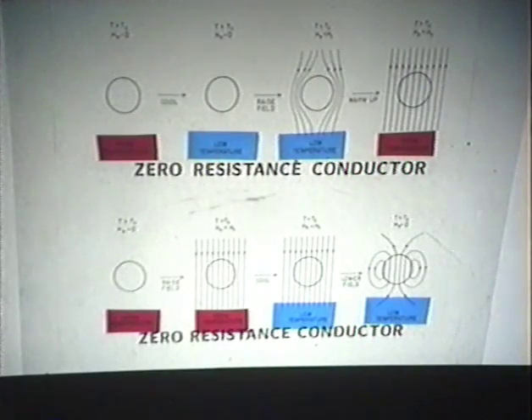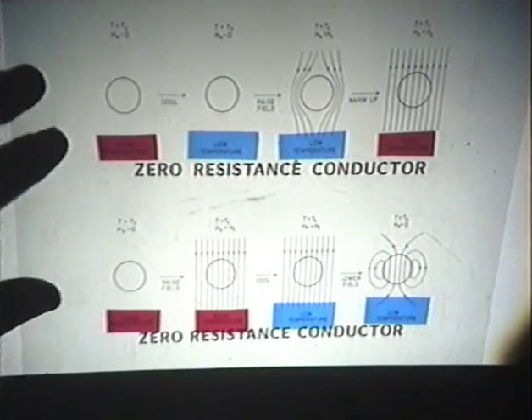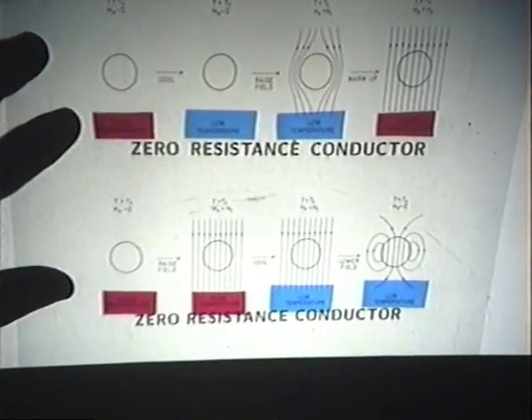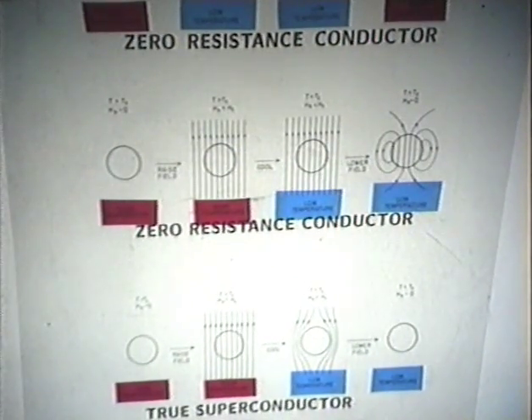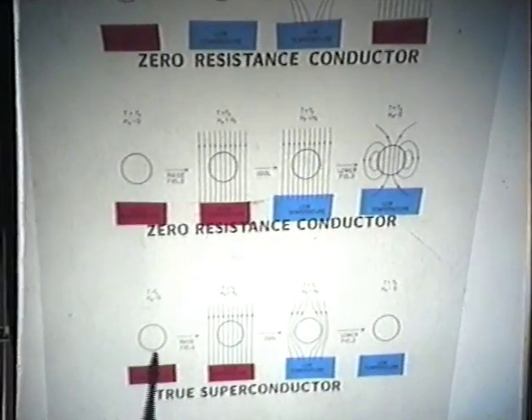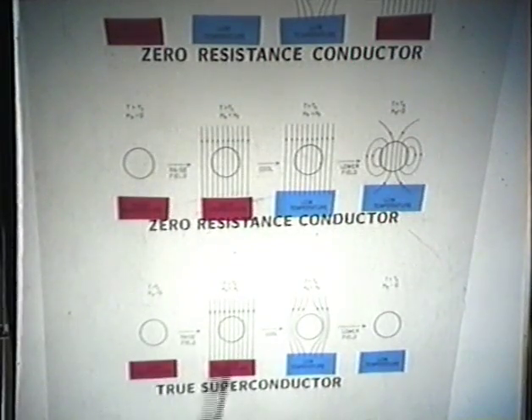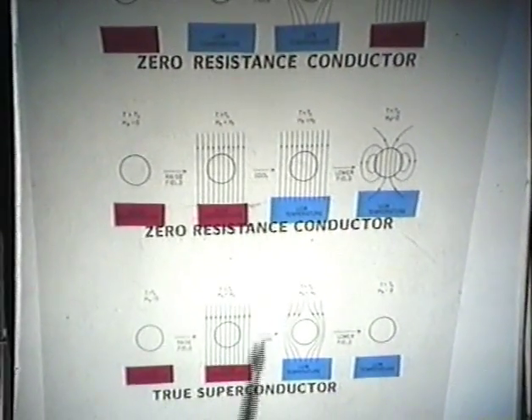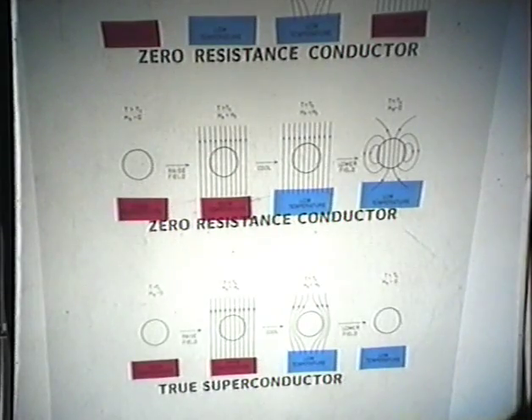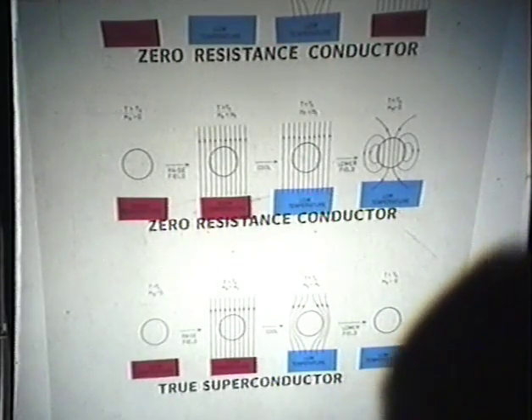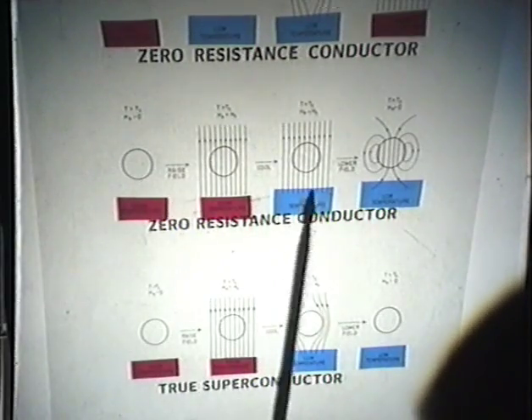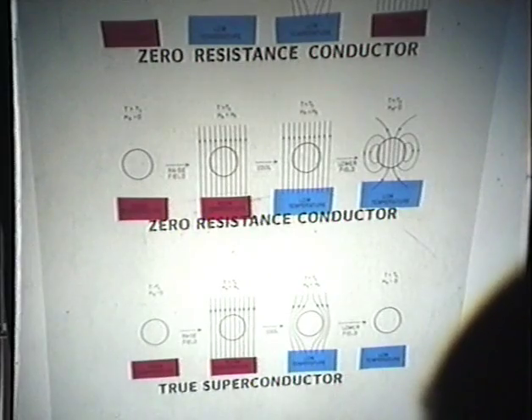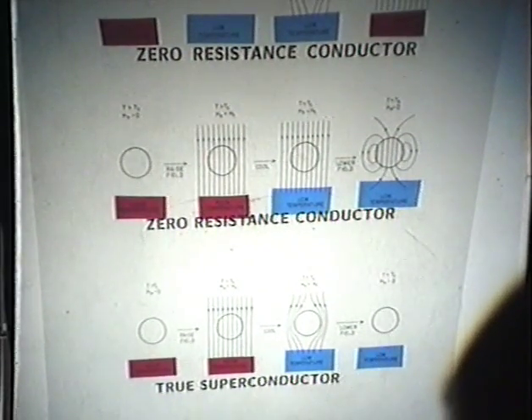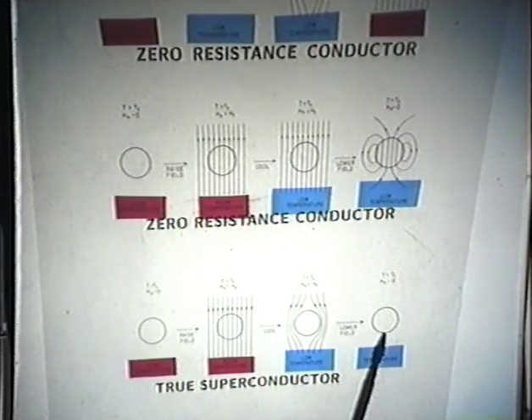So people did these experiments with the superconductors, these ones, niobium and lead and mercury and so forth. And this is what they got. A sensational result. When they took the superconductor at room temperature, put it in a magnetic field, and then cooled the superconductor down, even though there was no change in magnetic flux, the field was expelled spontaneously from the center of the superconductor. Completely unexpected from the behavior you'd have expected with a classical zero resistance conductor. And consequently, because the field is not penetrating into the center of the superconductor, when you lowered the field, it just returned to the unmagnetized state. There's no field left anymore.